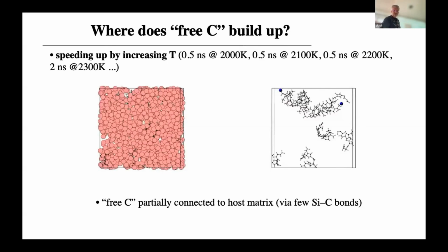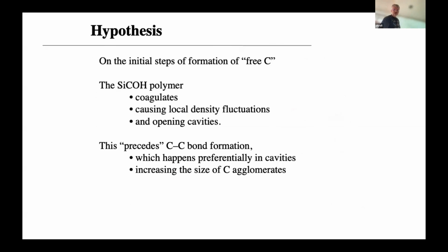However, the important part is it takes an awful long time, this so-called free carbon. We think we are reasonably motivated to claim, based on these simulations, that the SiCOH polymer coagulates, forms areas with higher and lower density, call this a cavity.